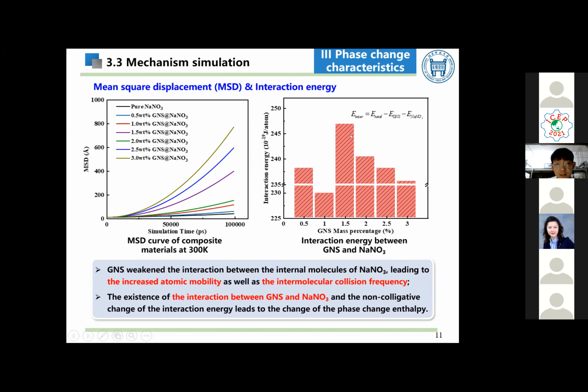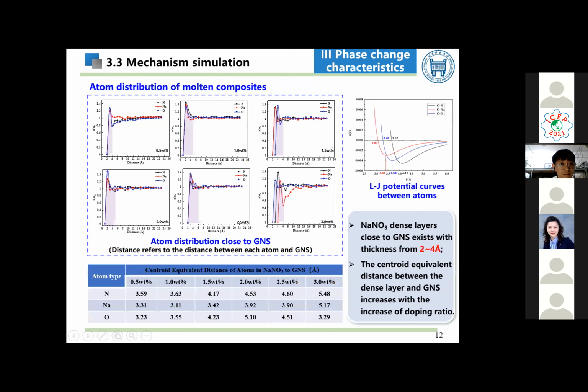Meanwhile, the interaction energy between GNS and the sodium nitrate was calculated. As the doping ratio increases, the change trend of the interaction energy is exactly the opposite of the phase change enthalpy. It is obvious that the non-colligative change of the interaction energy leads to the change of the phase change enthalpy. To account for the above change in interaction energy, the atomic position distribution of the composite was calculated by taking GNS as the origin.